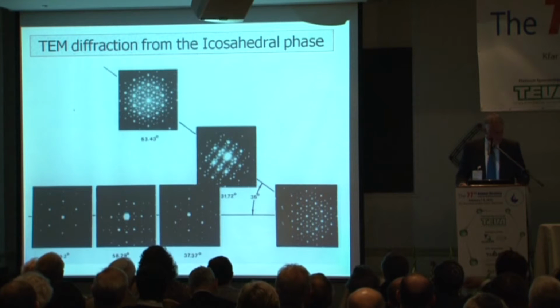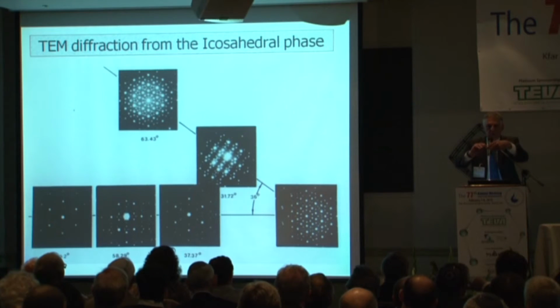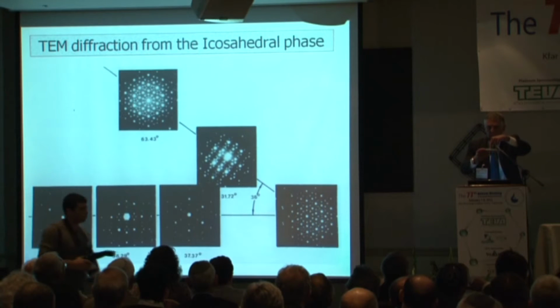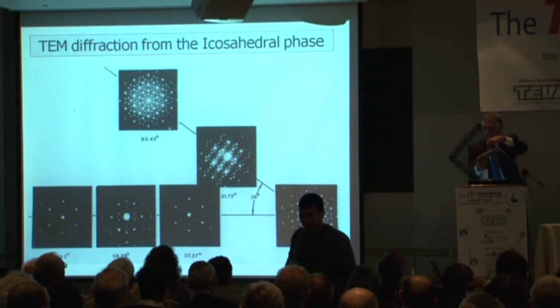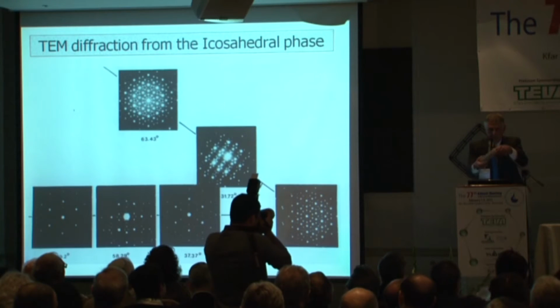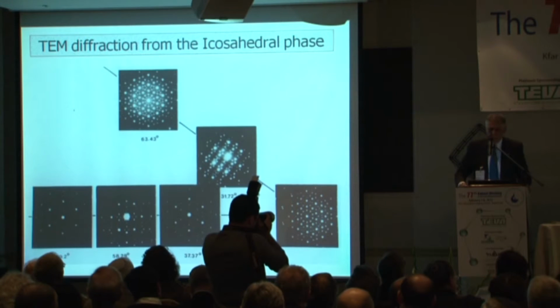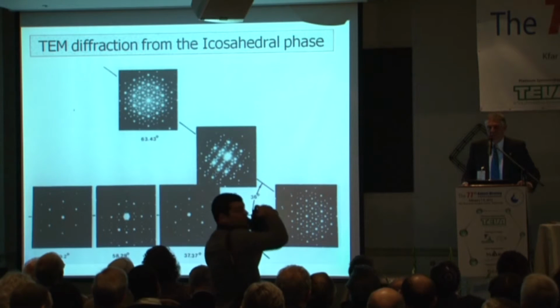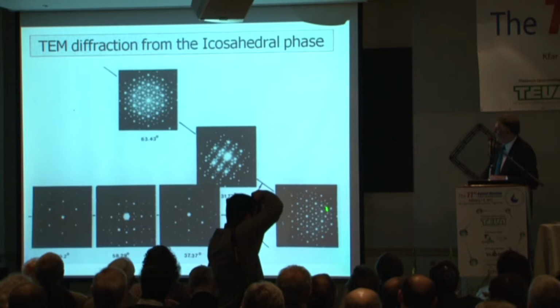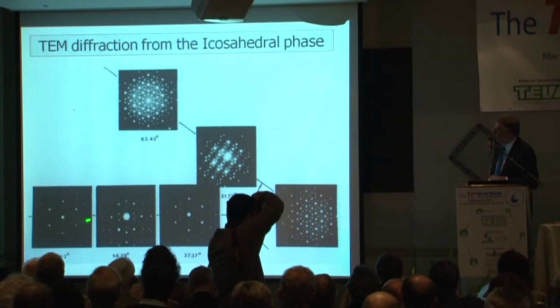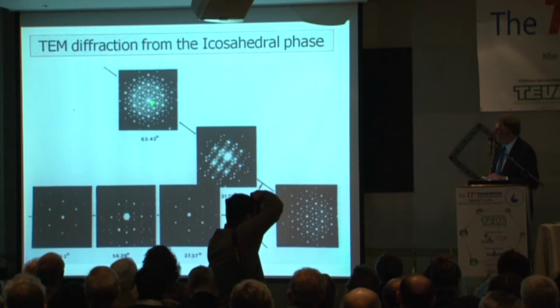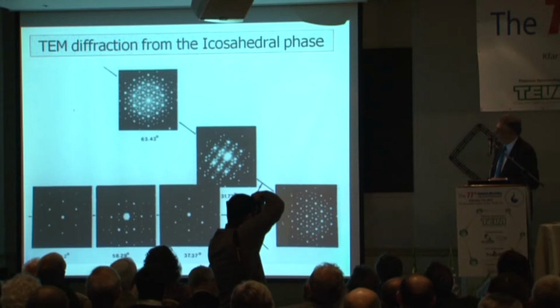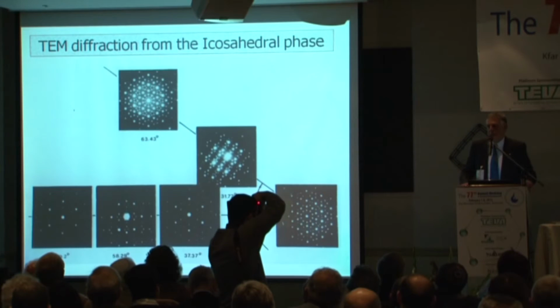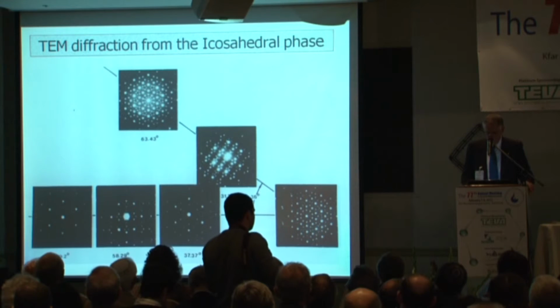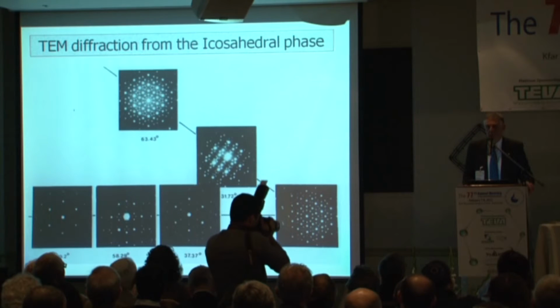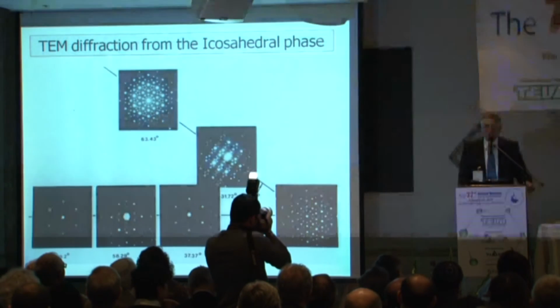So the other diffraction patterns, that means the following. Let's say that this is the specimen in an electron microscope. So I take a diffraction pattern from this orientation, and then tilt it, and take a diffraction pattern from this orientation, and tilt it this way. I can tilt it and rotate it each and every way I want. And so these are all the meaningful diffraction patterns that emerge from that crystal. And so what you have here is actually 5-fold, 5, 3, 2-fold, 3-fold, in another direction 5, 2, and another 5. So this set of diffraction patterns defines the crystal as being icosahedral in symmetry. And that's why we named this first crystal that was discovered the icosahedral phase.